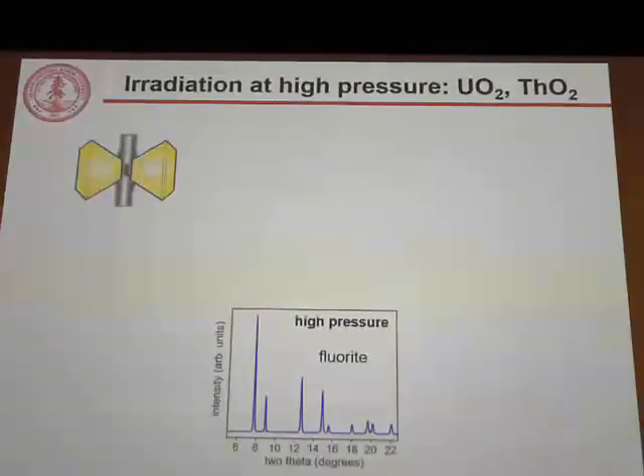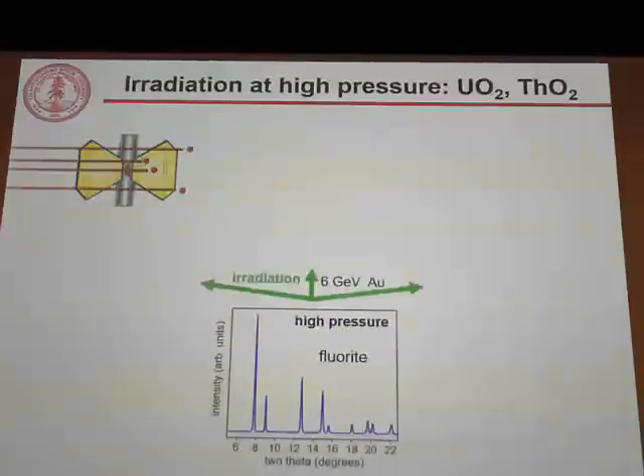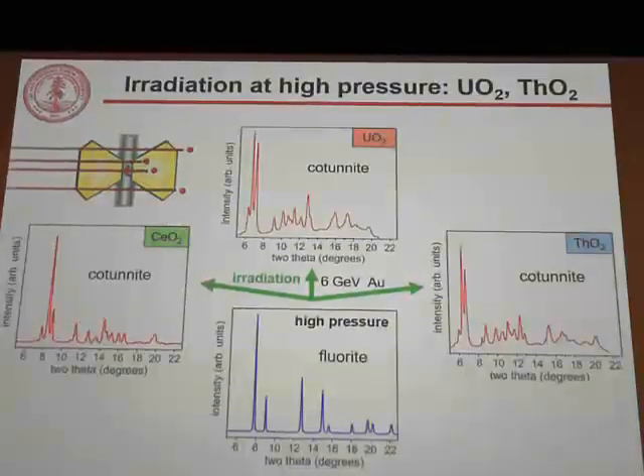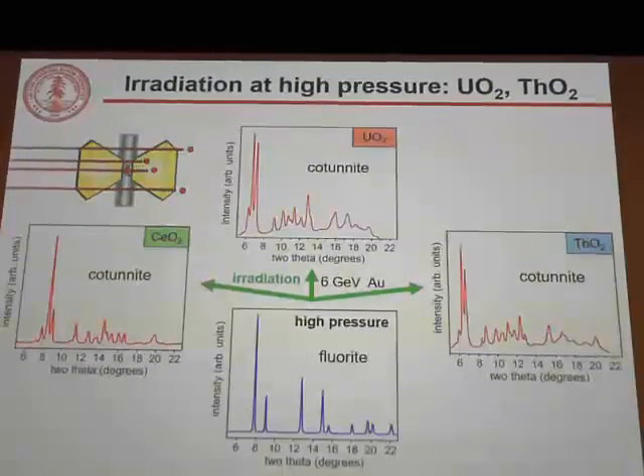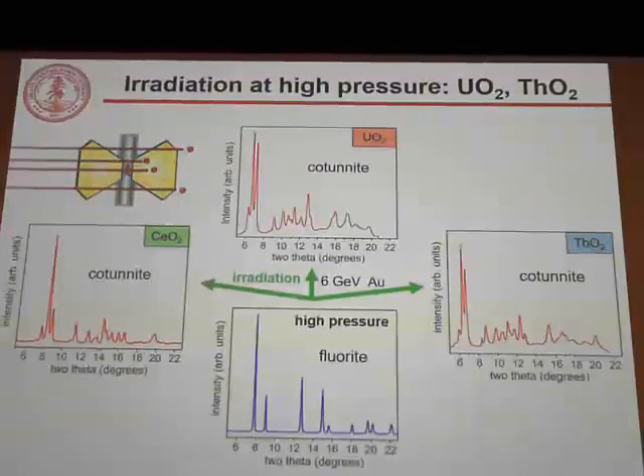We pressurize them to a pressure at which they maintain the fluorite structure, irradiate them while at that pressure, and for all three materials we see transformations to the same cotunnite phase. So we've produced this material at pressures below that which has previously been produced using this extreme environment of swift heavy ion irradiation coupled with high pressure.